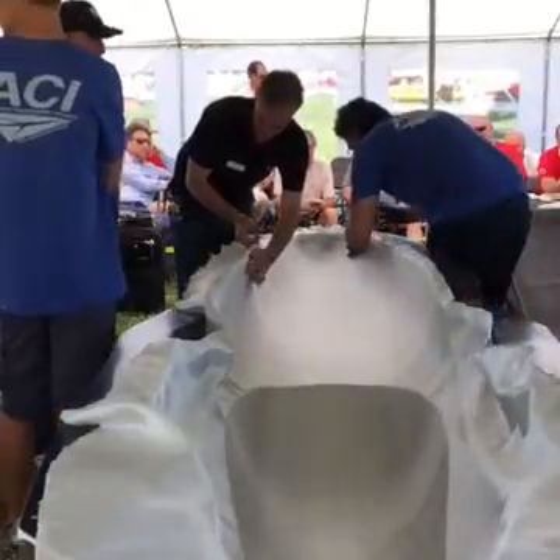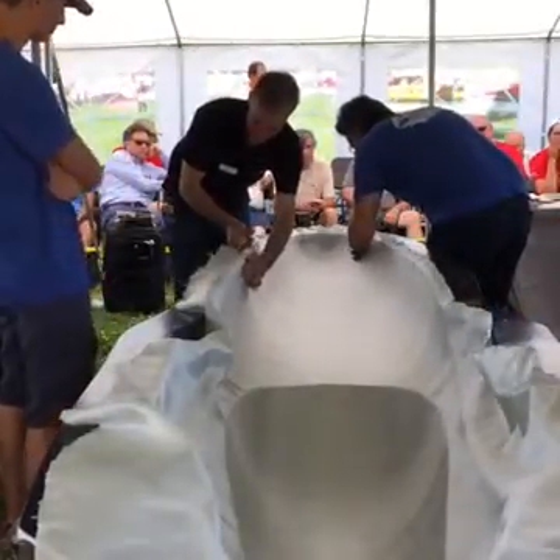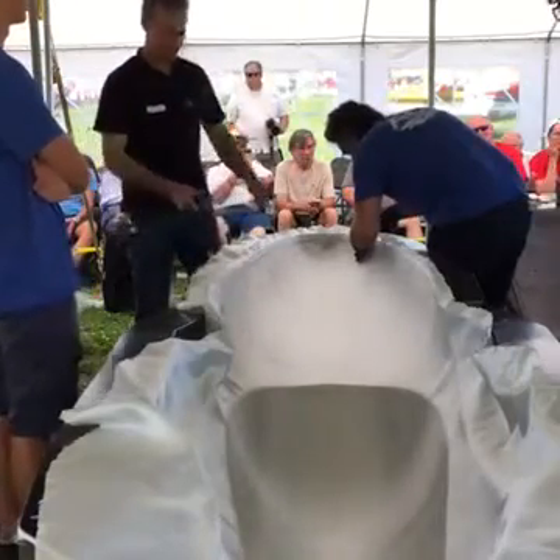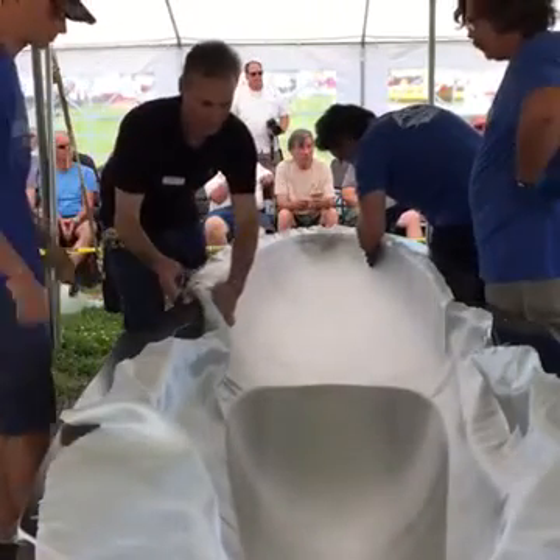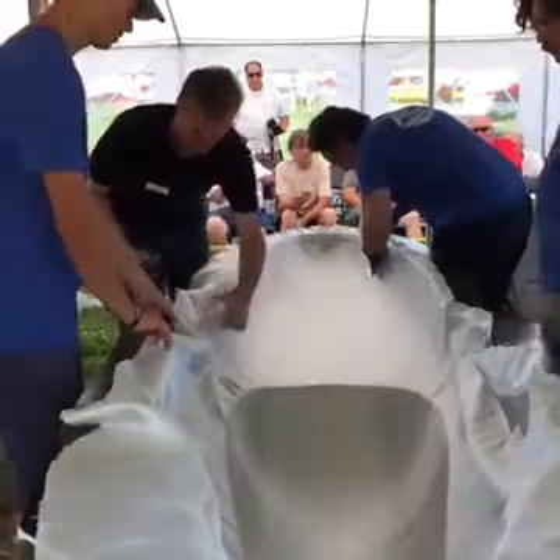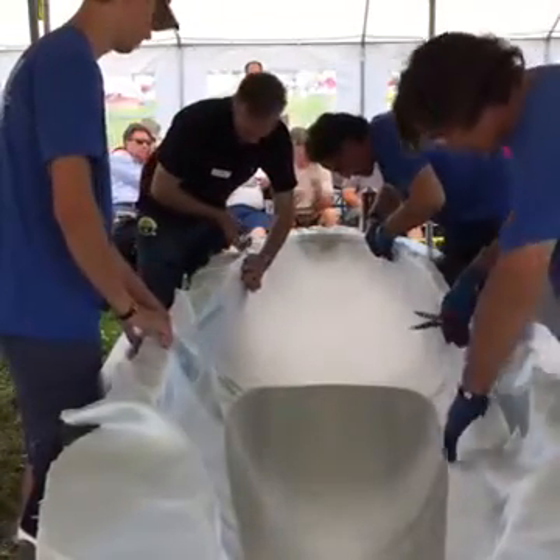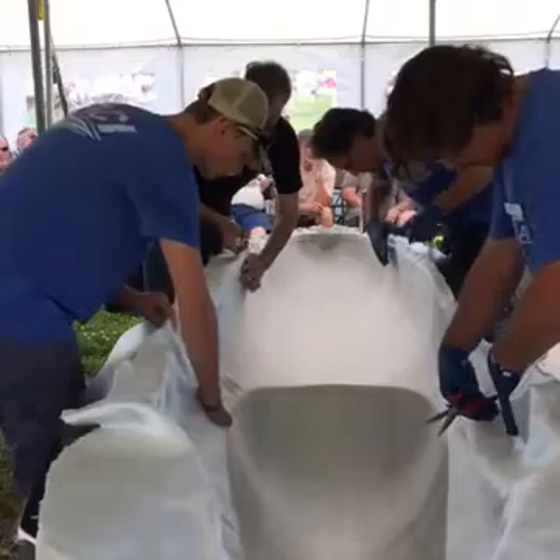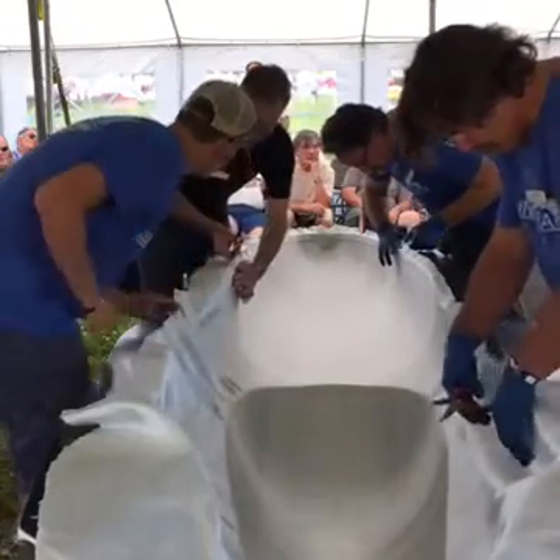So the question is, how do you do secondary bonding to epoxy parts? I would recommend every epoxy, like I said, it's different. I don't know what amine we're using. Amines will give you a blush on the surface. It makes it very difficult for other products to stick to. Epoxies usually don't have a problem. Some other products do, so I would check it.